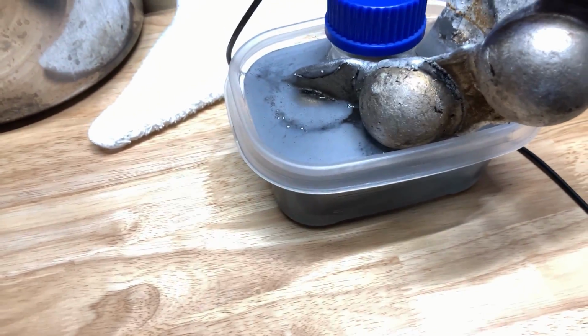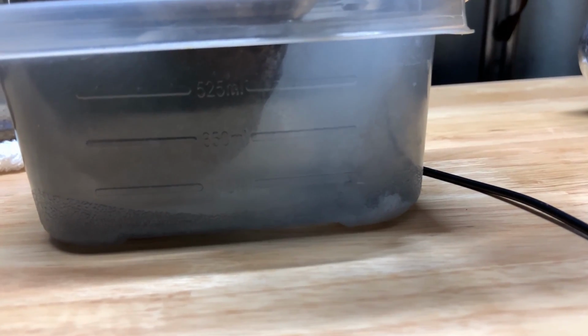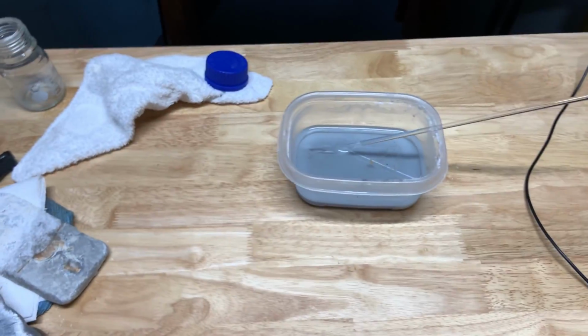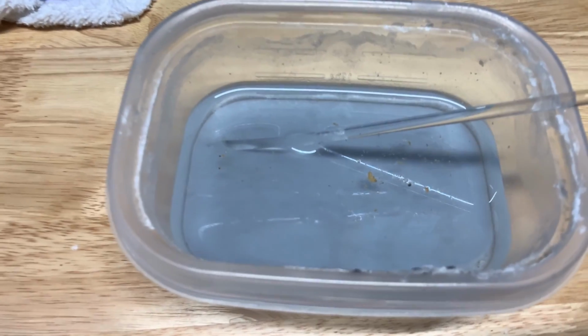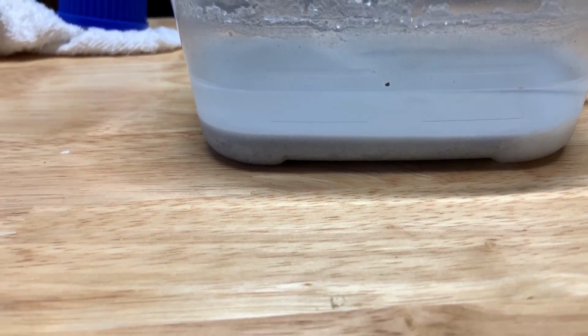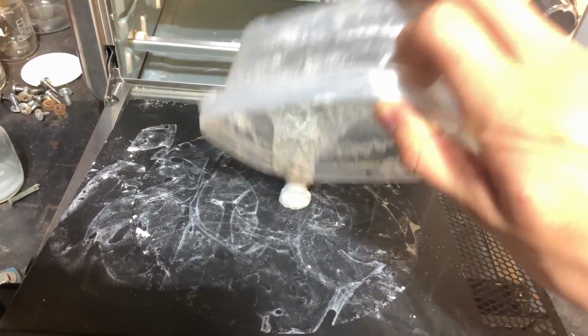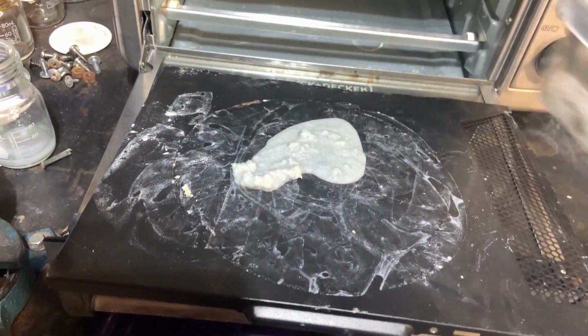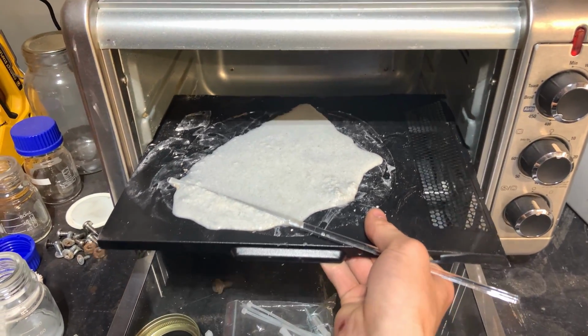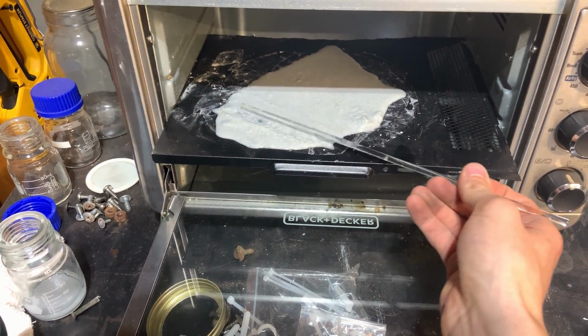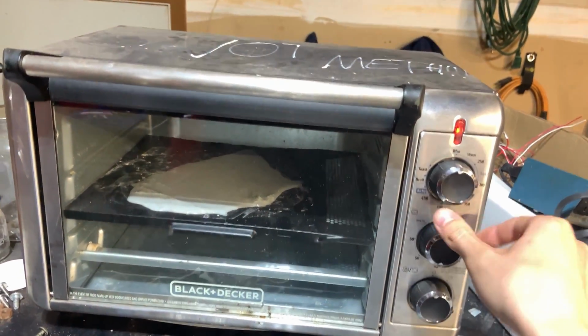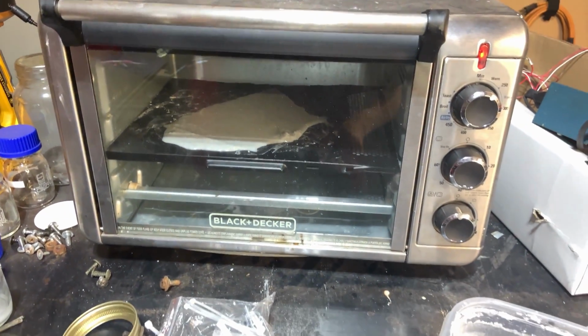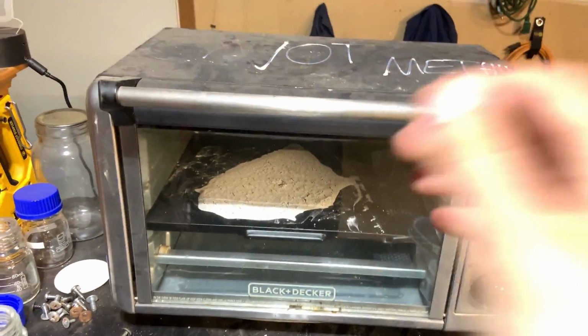For this new setup, I used 2 aluminum electrodes because I wanted to see if it was actually the stainless steel pot that was causing the solution to turn orange, and I used a little less Epsom salt this time, but you'll see it wasn't quite enough. After the electrolysis ran for about a day, I took out the solution and then I transferred it over to my little oven to dry it out. And here is the dried powder.